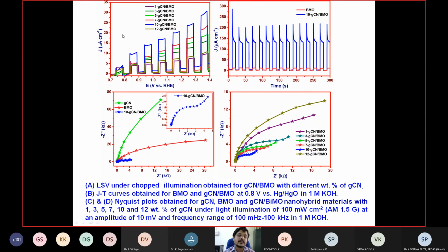Later, in the same linear sweep voltammogram experiment, we chopped the illumination. That means we switch the light on and off frequently. As a result, whenever we switch off the light, the current comes down, and whenever we switch on the light, the current goes up. So we varied the potential as well as switched the light on and off with respect to time. While increasing the potential, the photocurrent density also increased. The rise and fall in the photocurrent is also observed.